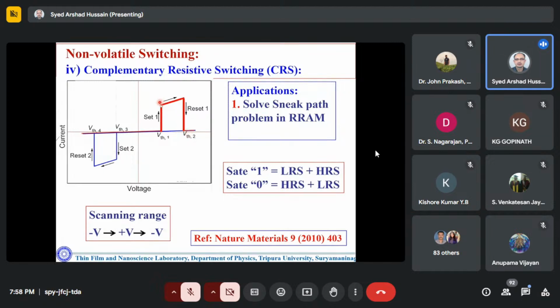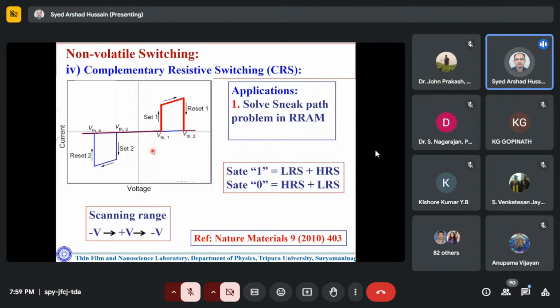So it retains the low conducting state up to this amount of time. The same thing happens for opposite polarity if you apply plus V to minus V. Unlike the earlier cases, say initially our device is in a high resistance state. So this is something like binary 0. Then at a certain bias, our system switches from high resistance to low resistance, which is equivalent to binary 1.